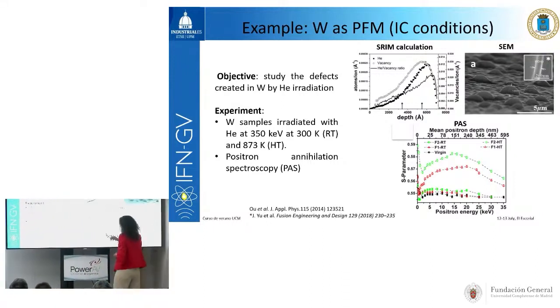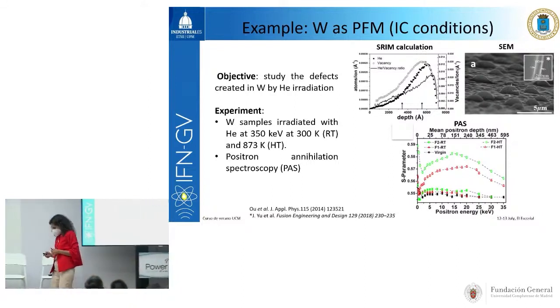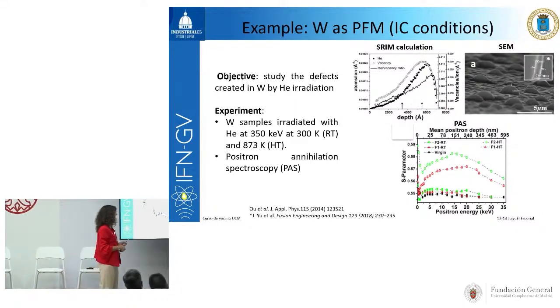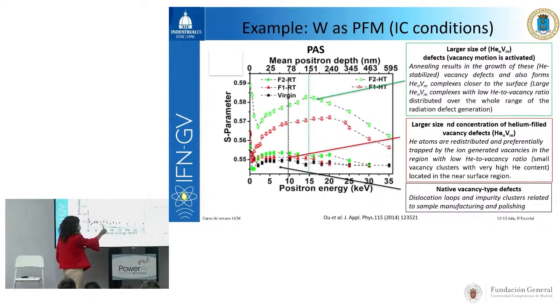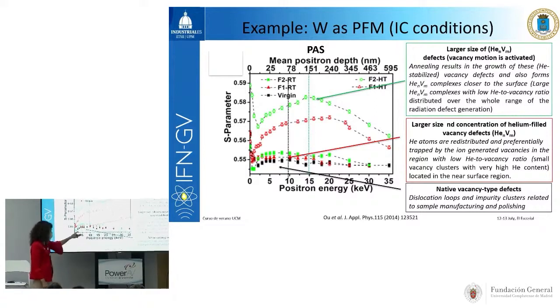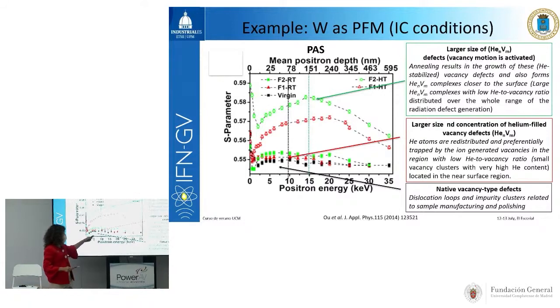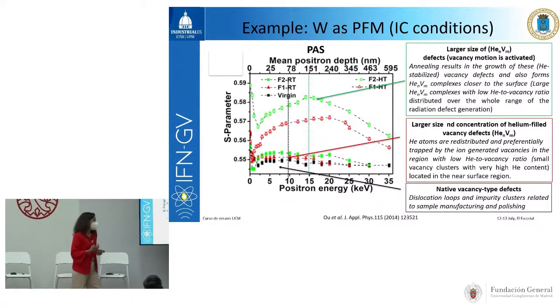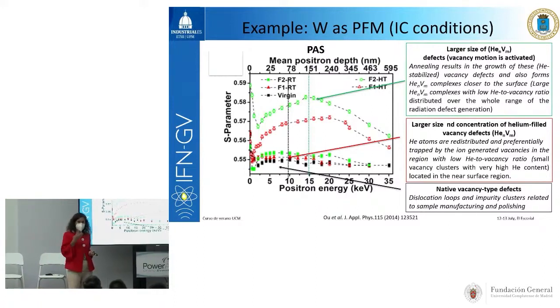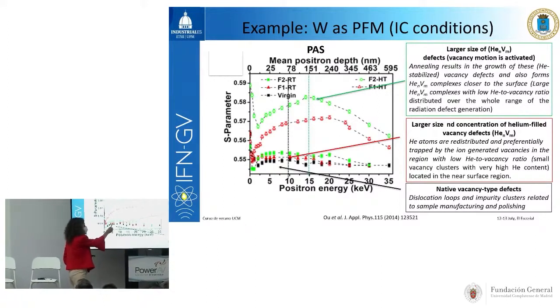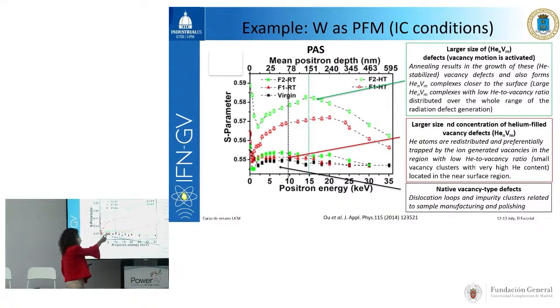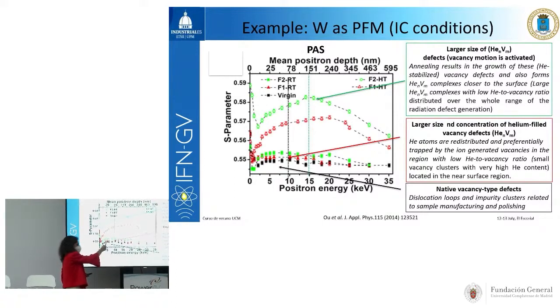Then if we analyze the behavior of the sample by using positron annihilation spectroscopy, the black line corresponds to the unirradiated state. Here we see a peak at 10 keV, which tells us that the sample already contains some defects before irradiation. Those defects are related with dislocations and impurity clusters, which are related with the manufacturing process or with the polishing process of the sample. Then we observe a small enhancement of the signal after irradiation, and a further enhancement after irradiation and annealing.